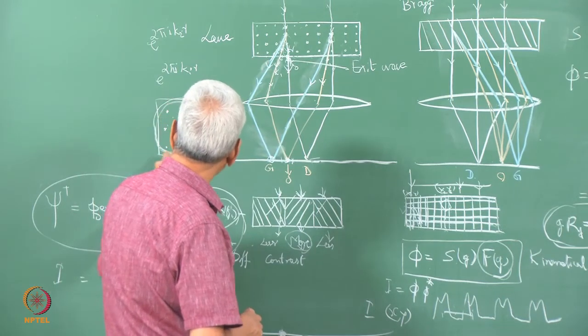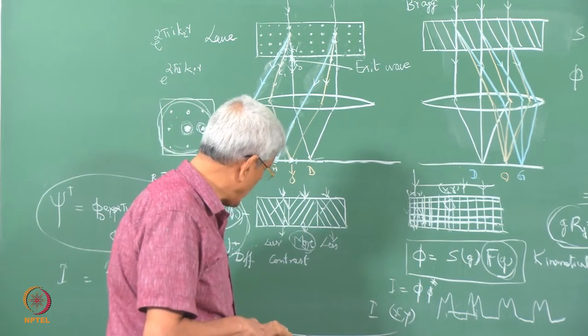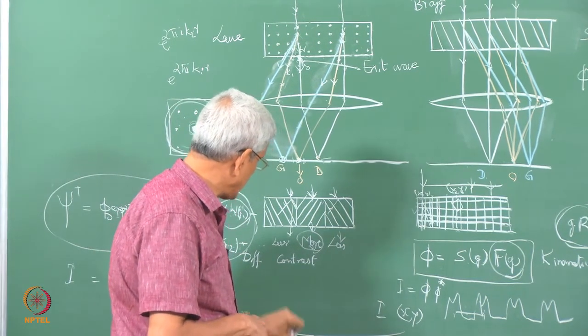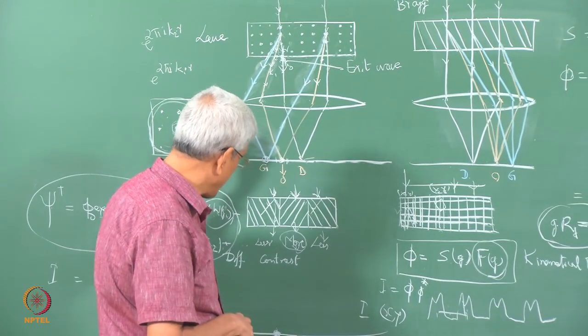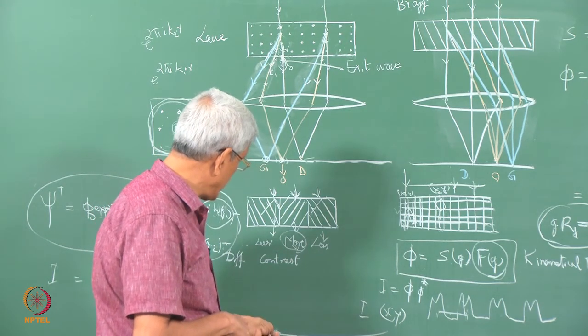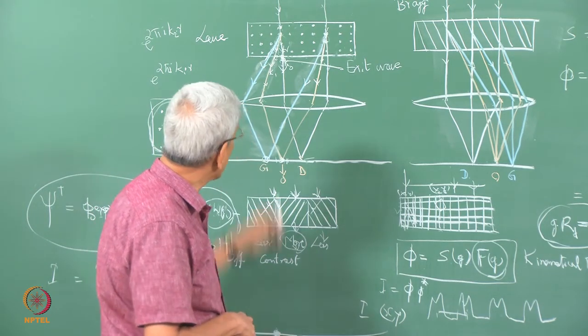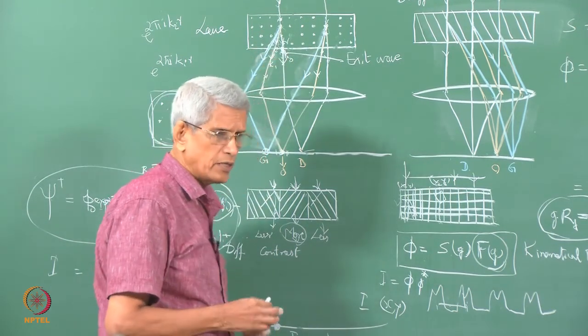If we take more diffraction spots and the image due to all of them is allowed to join and correct all the lens aberrations, and if the resolution of the microscope is such that it can resolve the separation between the atoms, then we should be able to see this high resolution image.